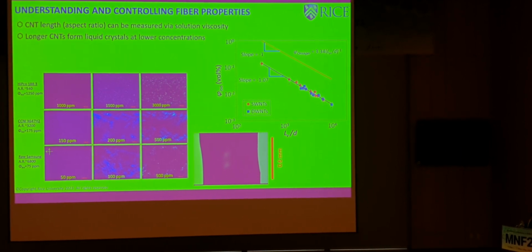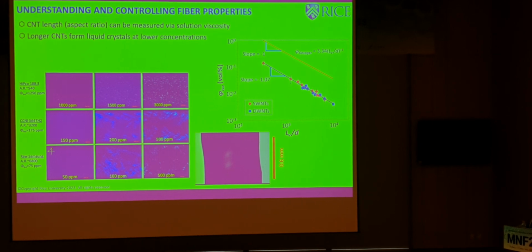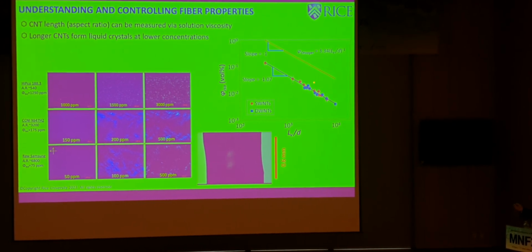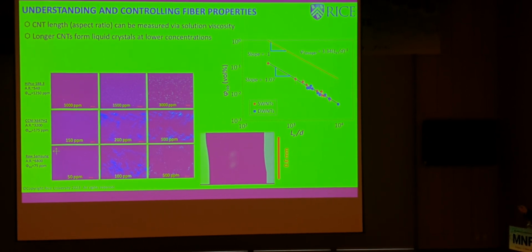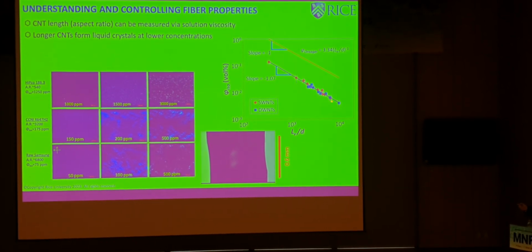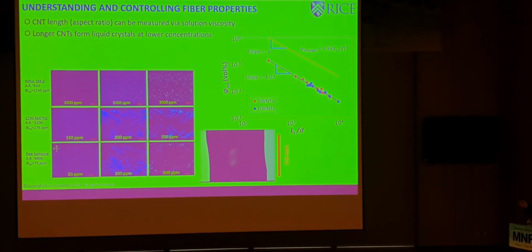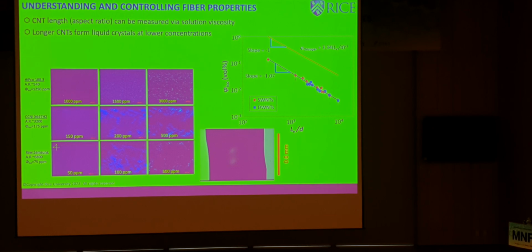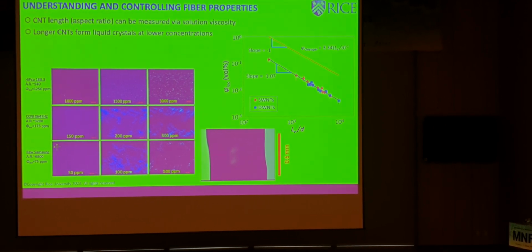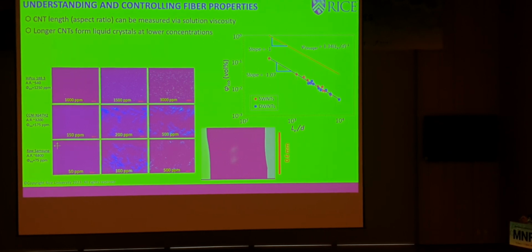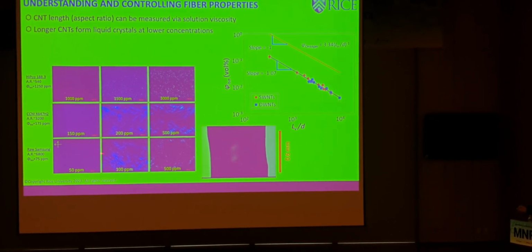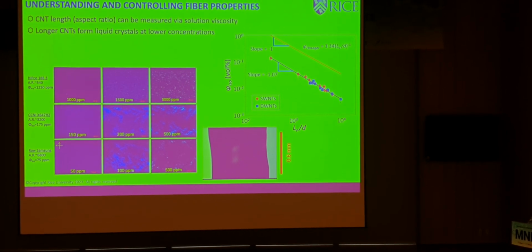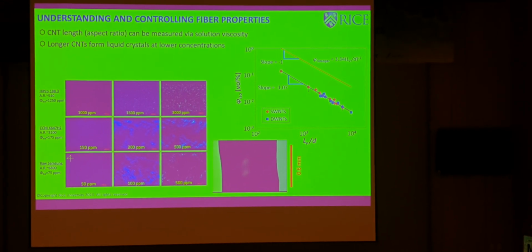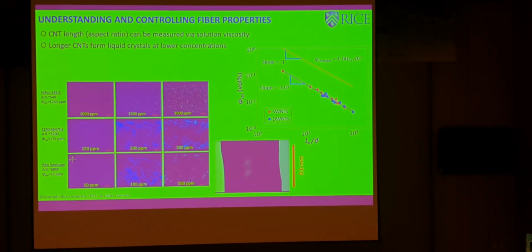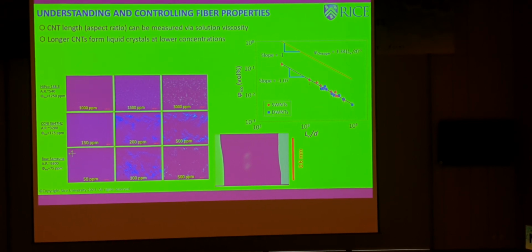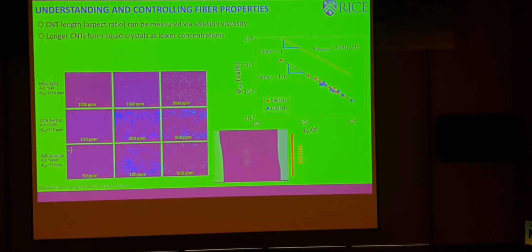And what we saw is that, again, as expected by classical theories, this transition from isotropic to liquid crystal happens as you increase concentration or as you increase length, and the two are related with this type of behavior. So as we had at the beginning, the transition goes as the inverse of the aspect ratio, where the aspect ratio is length to diameter. So here you see shorter tubes, these are HiPco, longer tubes, these were from Samsung when Samsung was still making nanotubes. And as you go up in aspect ratio, your transition from isotropic to liquid crystal happens at lower and lower concentration.